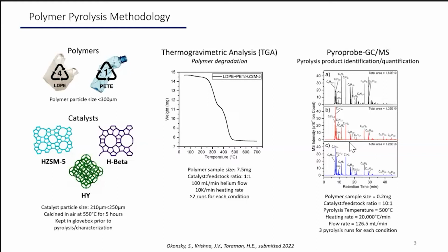And how we did this is using two different instrumental techniques. The first is called thermogravimetric analysis, TGA for short. And what this measures is at what temperature is the polymer degrading into pyrolysis vapors. The other instrumental technique we used is what is called the pyroprobe GCMS. And this is able to identify the pyrolysis products which are formed and is able to quantify the relative amount of these products which are formed during our pyrolysis.